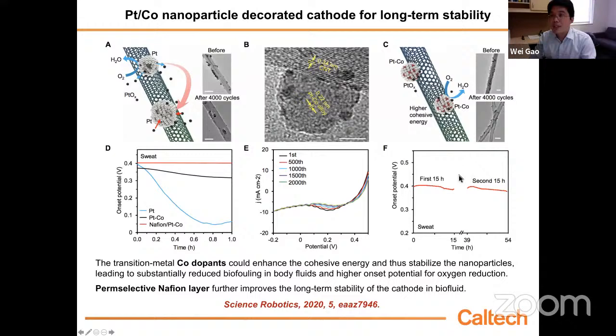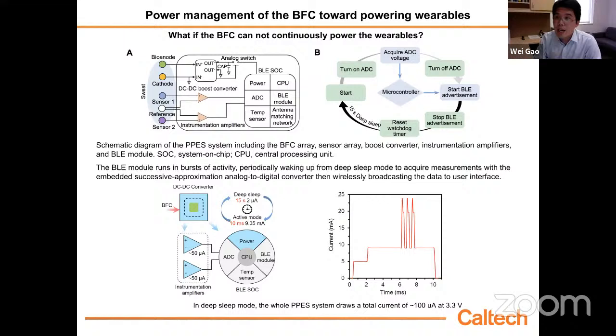If we store this biofuel cell for another 24 hours, then use it for another 15 hours, you see the onset potential remains nearly unchanged. They are very stable. And we did a very interesting power management. We want to make sure that even if our sweat contains a very low lactic acid level in some cases, we can still get enough power to power the entire system.